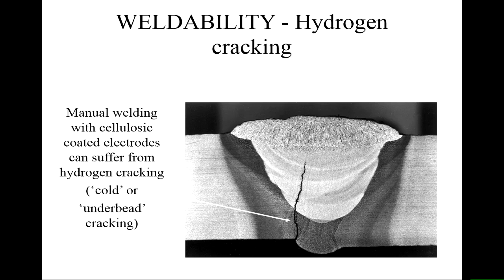And we've got some penetration issues here. We've got a penetration bead. Look at this part of the steel and this part of the steel, they don't match up, so there is an alignment issue here, and we've got a change in cross section which leads to stress concentration. And then we've welded with cellulosic electrodes which have not been dried, and hydrogen is produced, and hydrogen makes the steel brittle, and we get hydrogen embrittlement. So this crack comes straight through there from the hydrogen dissolving in the weld pool and then embrittling it as